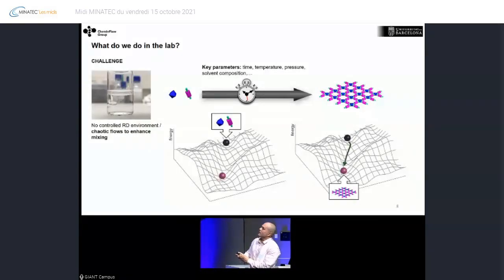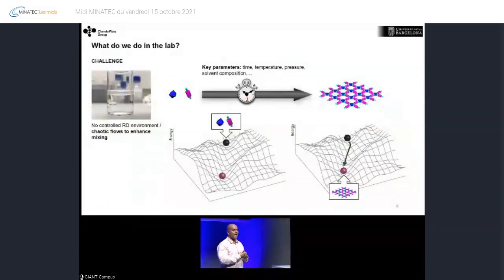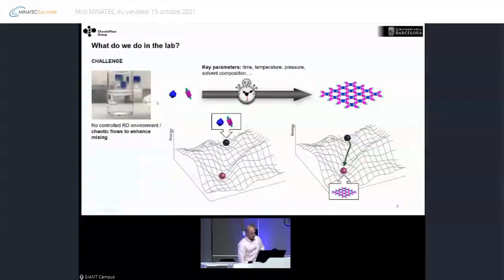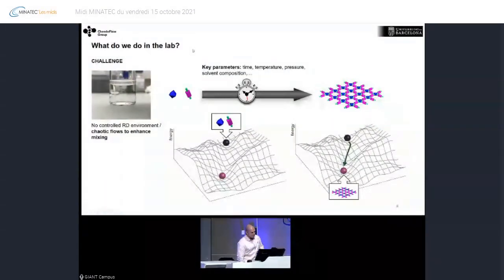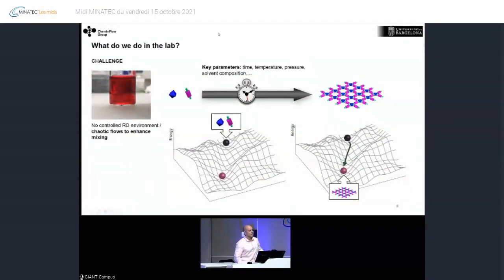So the first thing that an organic chemist will do is to synthesize molecules that will have functional groups that ideally will then self-organize, generating this 2D material. So how are we going to do that? As I said, the typical thing to do is to use turbulent mixing, so to enhance the reaction kinetics. And here, as you can see, we have no control over the diffusion, so we have depletion zones. This is not well controlled.